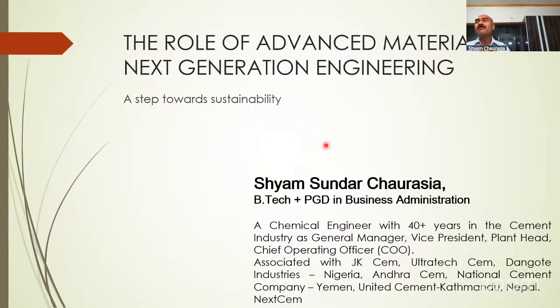At that time alumina refractories were available, and we were finding that every second month, especially in the burning June, where the temperature is the highest, the lining was going and we had to stop. Every cement plant had to stop within 2 to 3 months. That was the lifetime of the kiln running, the cement plant running. Apart from other downtimes, this was one of the key factors where cement plants were not able to run more than 2 or 3 months on average.